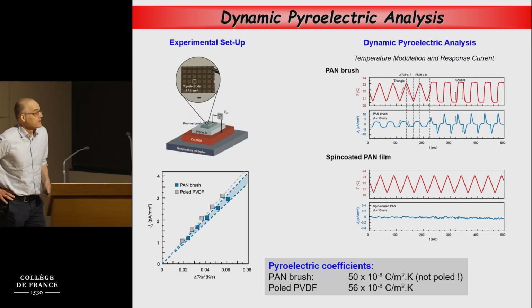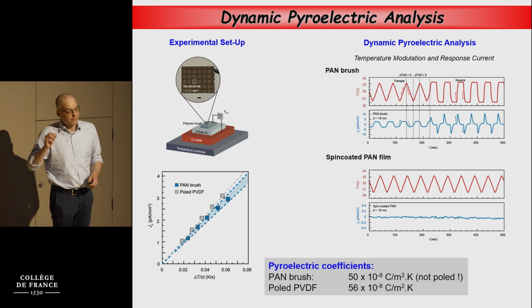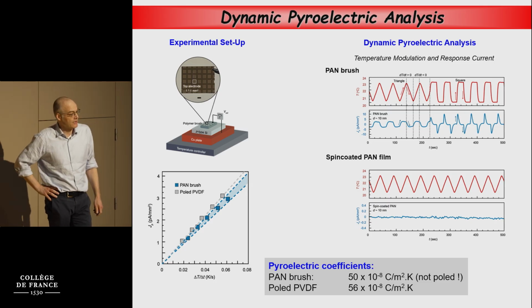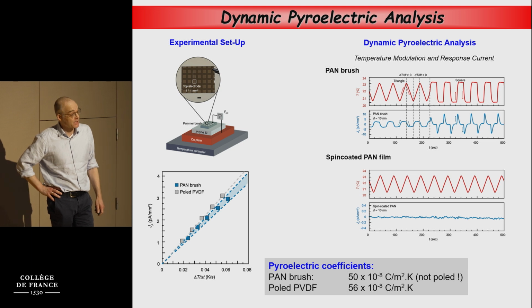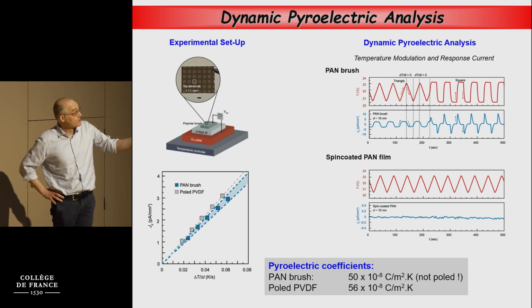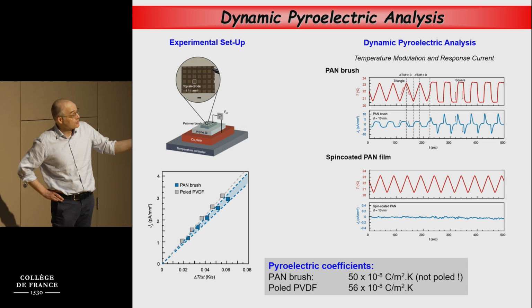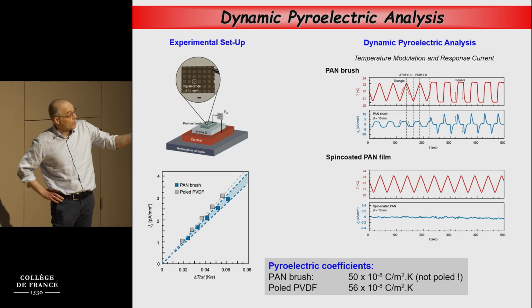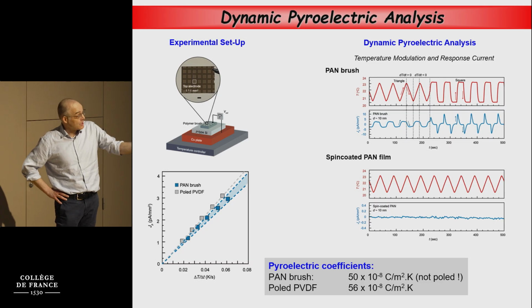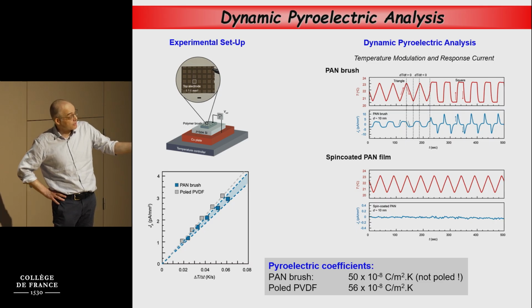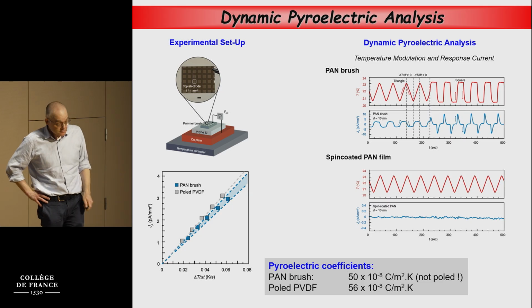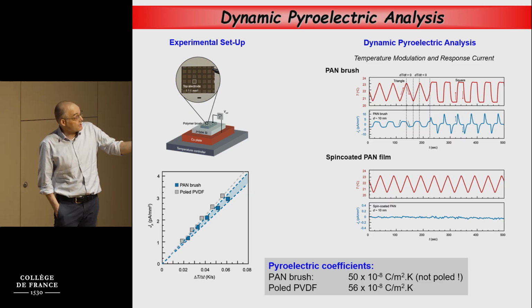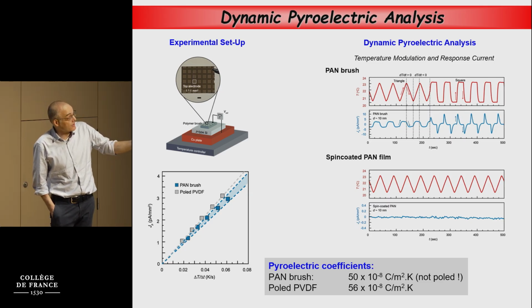What we did was, we grew very thin polyacrylonitrile brushes via surface-initiated polymerization from silicon substrates, and we did the same experiments as I've shown to you before. This is the same type of setup we utilized before to probe pyroelectric properties. We prepared a polyacrylonitrile brush, about 10 nanometers in this case. We prepared a spin-coated polyacrylonitrile film, and the student also looked at a poled, commercially available PVDF film. And these temperature modulation, current response curves are very interesting, I think.